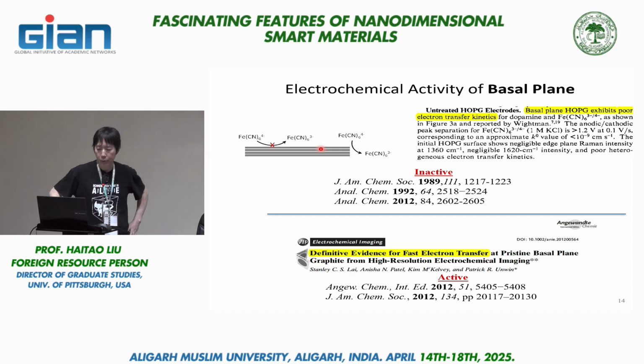Back in the 1980s, a lot of work was mostly done by McCreery's group, who was at Ohio State at that time. They demonstrated that basal plane graphite is electrochemically inactive, and the edge plane is electrochemically very active. At that time, it was understood that there's no specific adsorption on the basal plane. In addition, the electronic structure of graphite is such that the density of states is pretty low at the Fermi level, so that would support very sluggish charge transfer. So from both a surface chemistry perspective and a band structure consideration, people were happy with the conclusion.